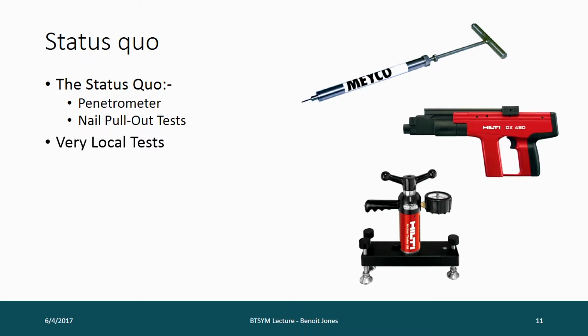The penetrometer, it's quite a big thing. It's probably that big, and you need to apply quite a lot of force to push it in quite a small distance. It's quite hard to know whether you've gone that distance, especially when the surface of the shotcrete's bumpy. You need to be quite a heavy person to even get it to 0.7 or 0.8 MPa. To measure anything above that is not really possible.